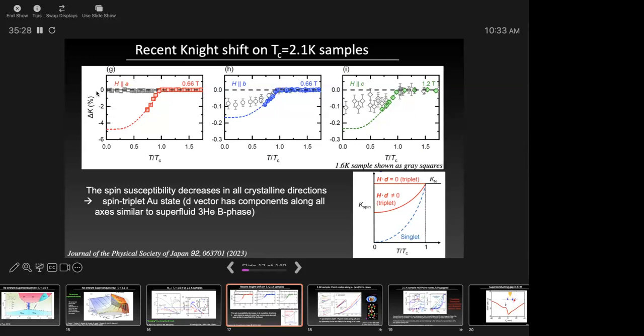The first samples, they saw no change across TC. Then they did some more measurements, and then they found this gray data where in the A direction, there's no change across TC. But in the B and C, there's a very small change, nothing like what you would expect for a singlet, okay?